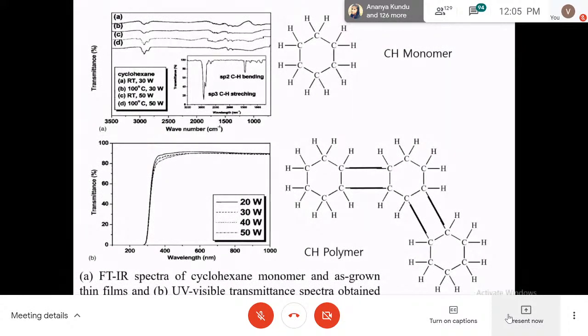We first send the cyclohexane monomer, and it is polymerized due to the plasma created inside the PCVD. The plasma, due to this electrical energy, breaks the bond, and then it polymerizes the cyclohexane monomer, and then we get cyclohexane polymer. And then when the deposition power, deposition temperature or deposition time is increasing, we get